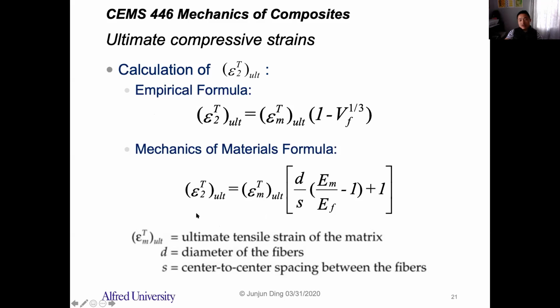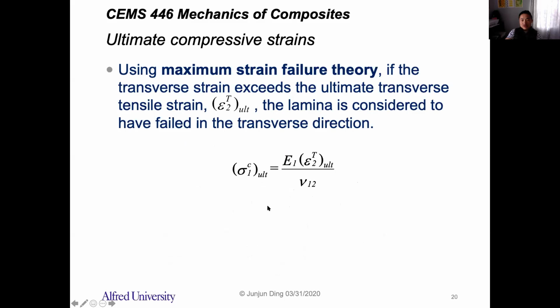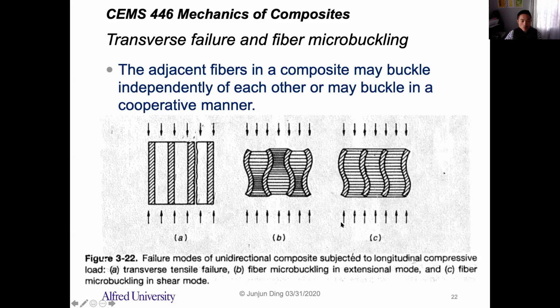And you can also get this ultimate strain from the mechanics of materials formula, which is calculated based on the ultimate strain of the matrix, the diameter of the fiber, the center to center spacing between fibers. So this is the arrangement of the fiber, right? And the Young's modulus of matrix, Young's modulus of fiber, you can calculate the ultimate strain in the two direction, so that you can use that in this equation to calculate the ultimate stress that can be applied in the one direction, right? Okay, so that is the case for the failure mode A, right?